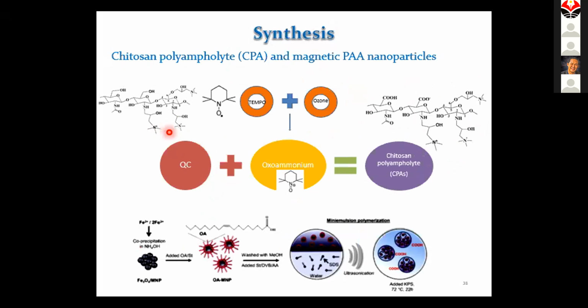Not only introducing positive charge, we also want to introduce permanent negative charge to the structure. So we oxidize the OH group into a carboxylic acid group that can deprotonate and become a carboxylate group with negative charge. Now our chitosan has both positive and negative charge on the same chain. This is called polyampholyte, or we call it CPA, and this works very well as an anti-scalant compound.